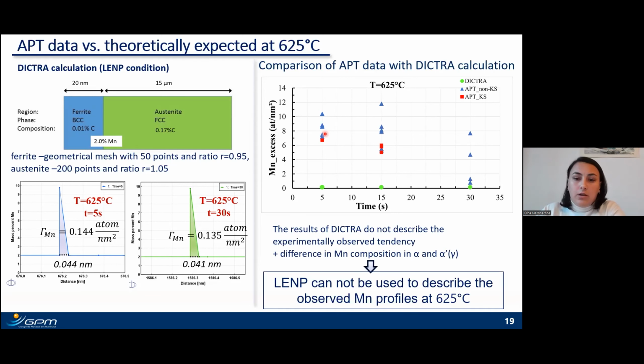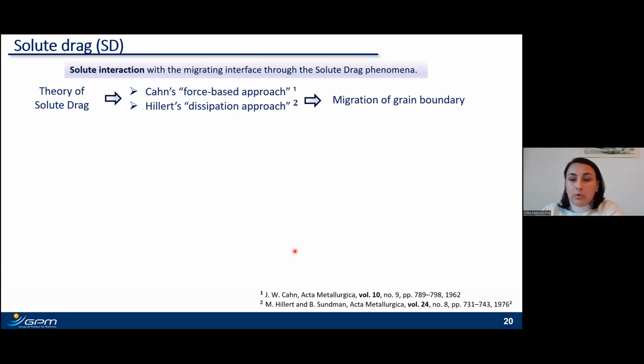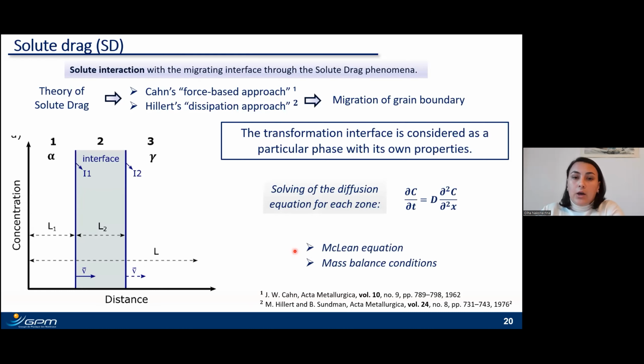Based on this data, we can conclude that LENP cannot be used to describe the observed manganese profile at 625. Therefore, we have to find another model that will better describe the experimentally observed result. Recently, the solute drag-based model started to attract more and more attention. It describes the interaction of solute atoms with the moving transformation interface through the phenomenon known as solute drag. One of the main assumptions of the solute drag-based model is that the transformation interface is considered as a particular phase with certain thermodynamic and geometrical properties.